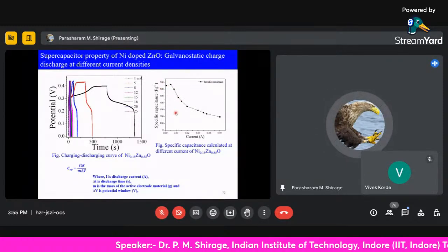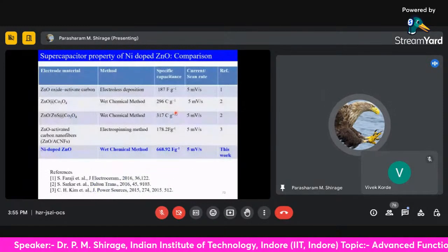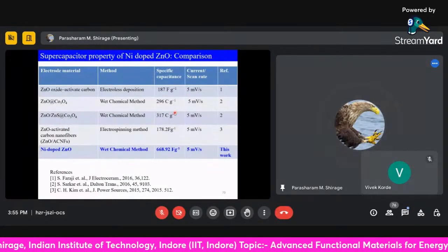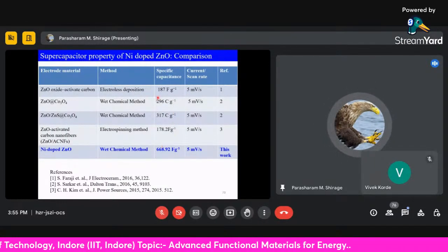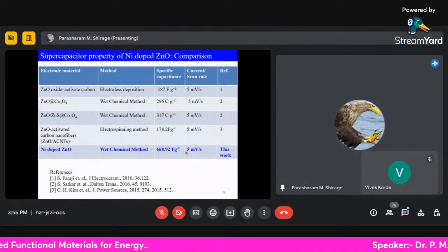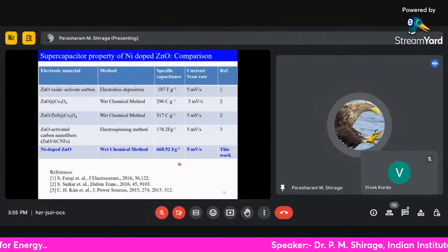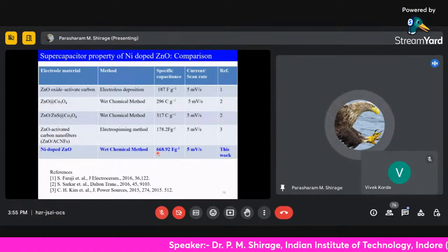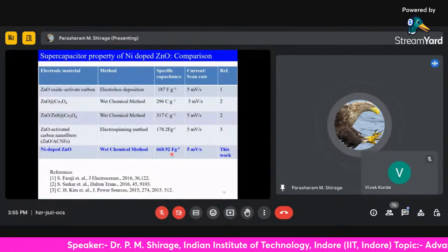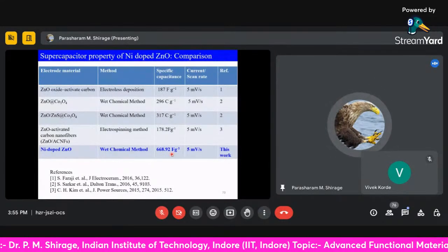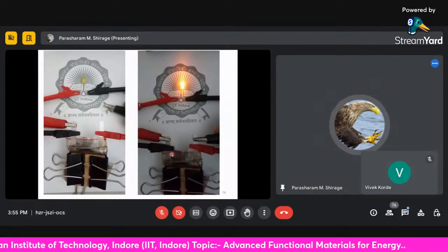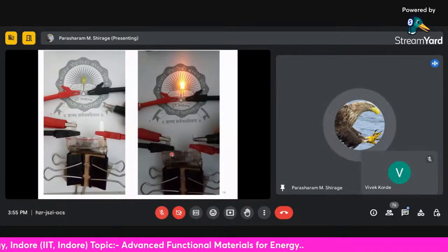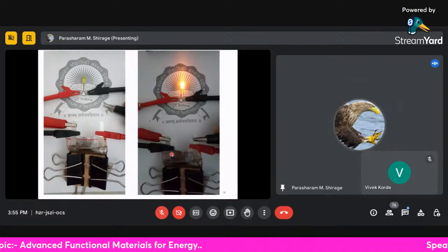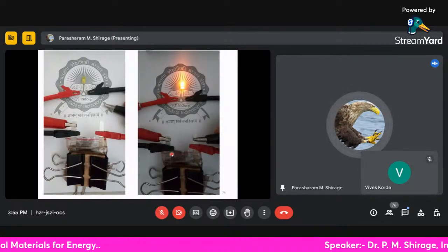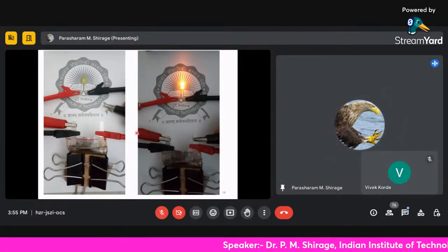Okay, so it means that this material has great potential, but compared with other people's work, where are we standing? Other people's work has a maximum specific capacitance of 317, but because of the controlled morphology and properties, we are getting about 700 Farad per gram, almost double that. So our work is potential for application, and this is a pouch cell supercapacitor prepared in our lab. One of the students, Dr. Pratik Bhojane, prepared this, and it was charged for 10 seconds, and it can light up this LED.